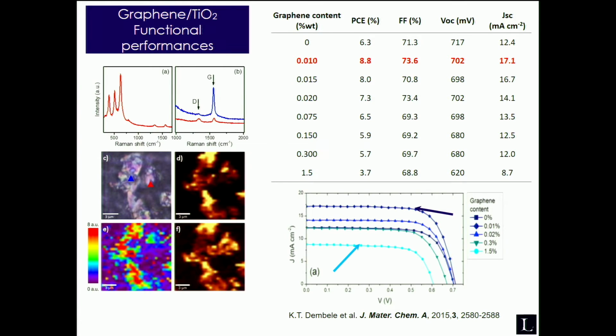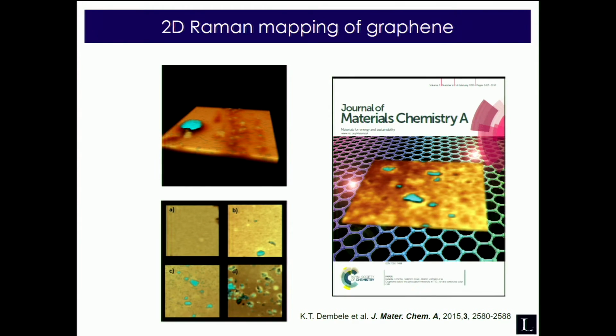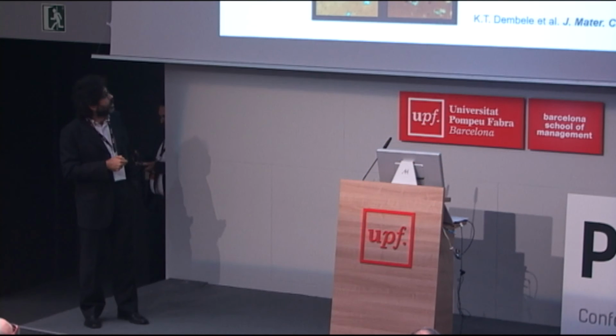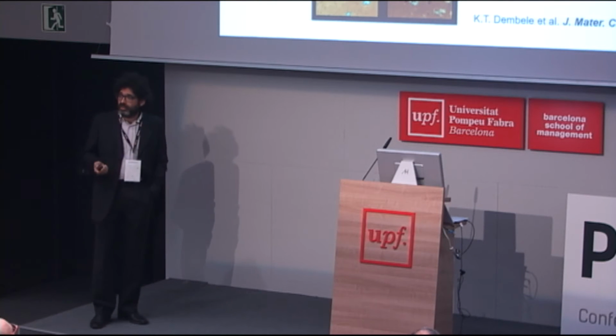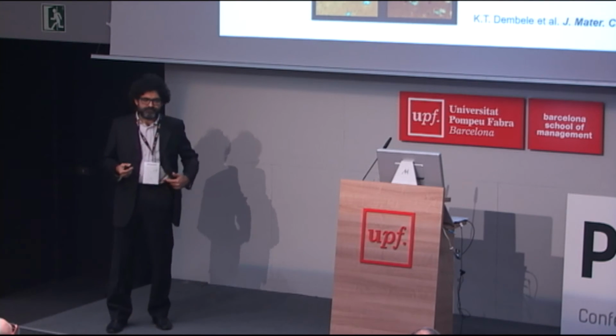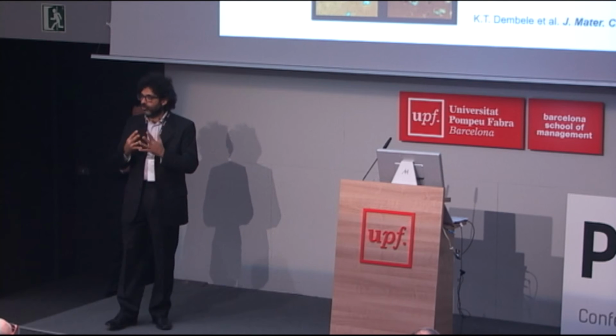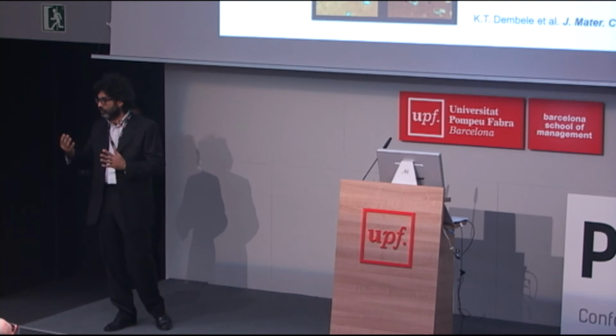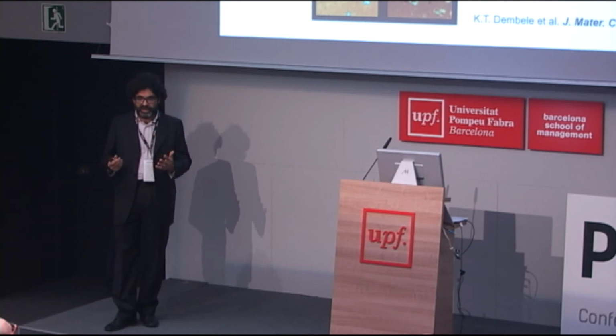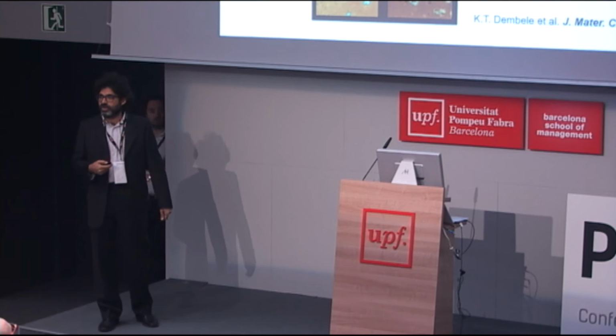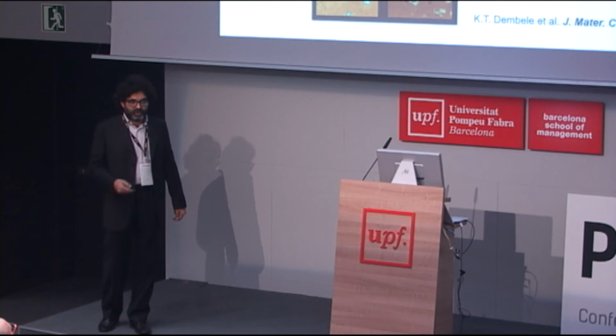However, we were surprised because if you look at the distribution of graphene platelets, shown as these blue dots, the best sample is this one. So the main idea was to create a connecting network inside titanium oxide for transporting charges, which is not the case here, since the graphene concentration is well below the percolation threshold.